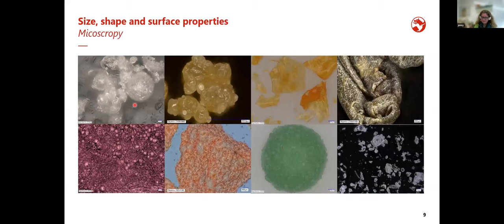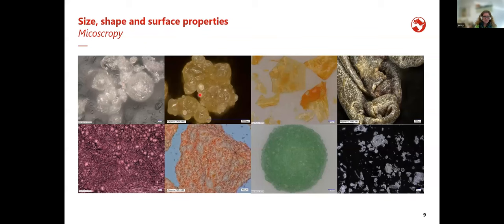The first picture shows a spray-dried product that did not go well: there's a wonderful sphere but all other parts look like broken glass — this is unwanted agglomeration. The next picture shows a wanted agglomeration: an agglomerated spray-dried product with visible primary particles. This demonstrates the need for care in measuring particle size. With a sieve size of, say, 200 microns, a particle can pass or be blocked depending on its orientation — so whatever comes out of particle size measurements is very often a distribution, not a discrete number.